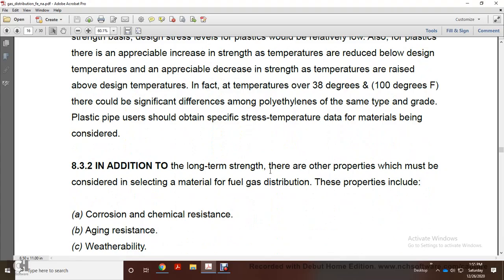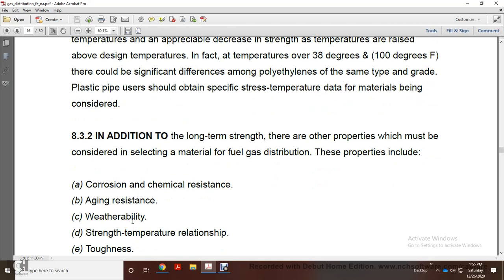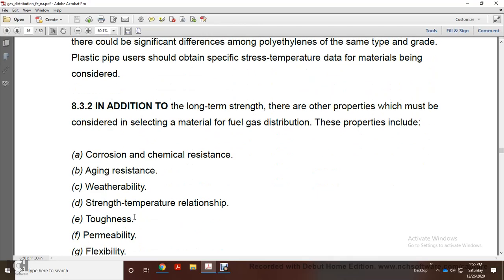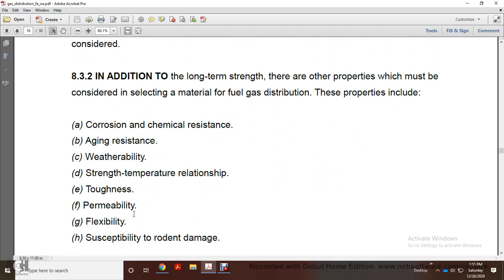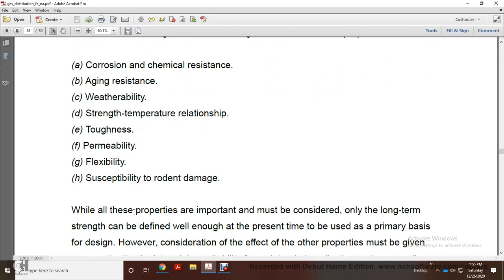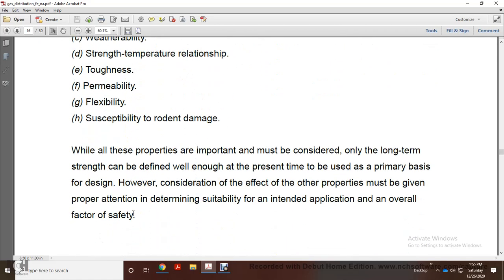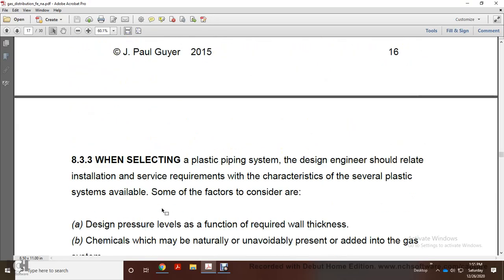8.3.2. In addition to long-term strength, there are other properties which must be considered when selecting material for fuel gas distribution. The properties include corrosion, chemical resistance, aging resistance, weatherability, strength-temperature relationship, toughness, permeability, flexibility, and susceptibility to rodent damage. With all these properties important, long-term strength is well enough defined at present to be used as the primary basis for the design. However, the effect of the other properties must be given proper attention in determining suitability for the intended application and the overall factor of safety.